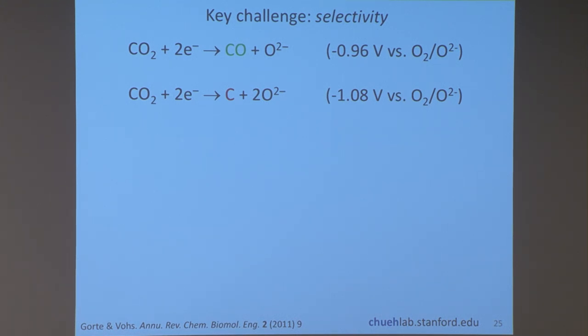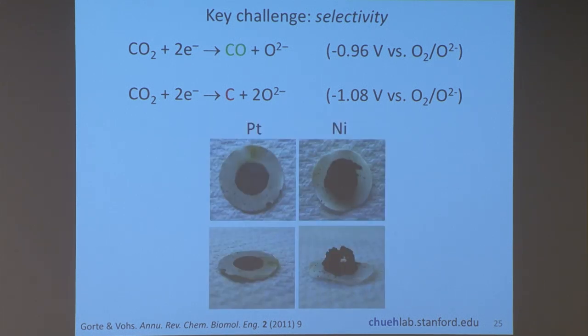But the problem is twofold. One, the potential for these two processes are very similar. They're only off by a little bit more than 100 millivolt. So it's very, very close. So you can get both of them at the same time. And then secondly, if you deposit carbon in an electrochemical cell, it's going to fracture your entire cell.